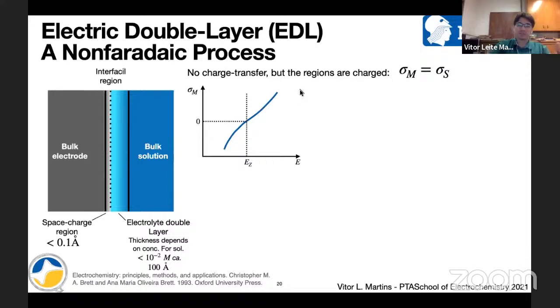There's no charge transfer, as I said before, but the regions are charged. So we have charge in the electrode surface, and we will have charge on the electrolyte region close to the surface of the electrode. And the important thing here is that the charge of the metal is equal to the charge of the solution. So the charge is balanced here. So the net charge is 0, but you have charging potential in metal and charging electrolytes.